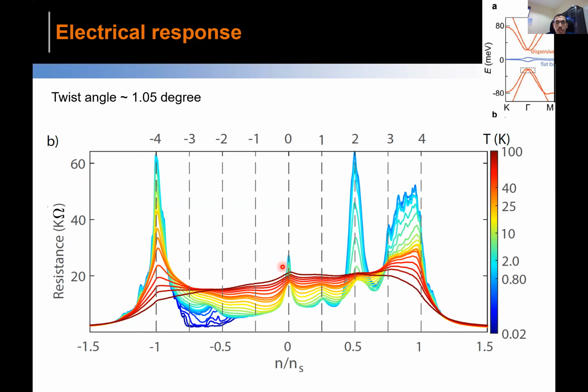So this is the response of the device now. This is the device I was talking about, from our group. As you can see, this is the density axis. This is your Dirac point, and this is the resistivity. At zero, you have this Dirac cone, as you expect. If you have a single layer graphene, the resistance should decrease monotonically. It will never have this kind of feature. On the other hand, here you see very funny features happening, and they are not symmetric between the electron and hole side. The most important thing you see first is another large peak at the 4-electron filling.